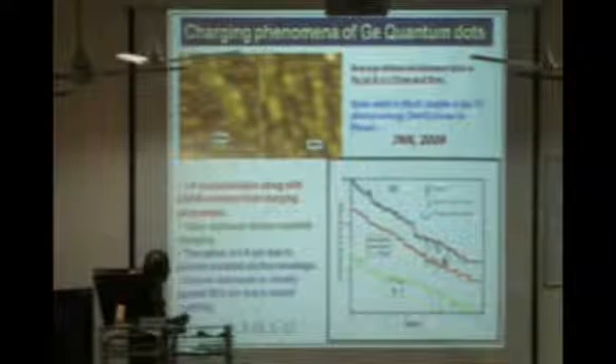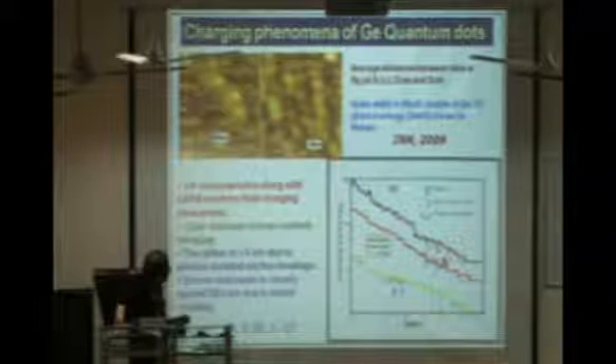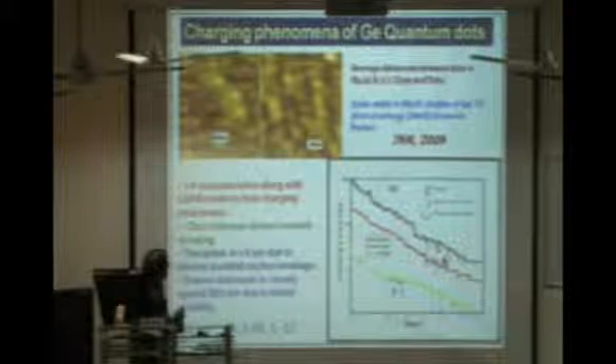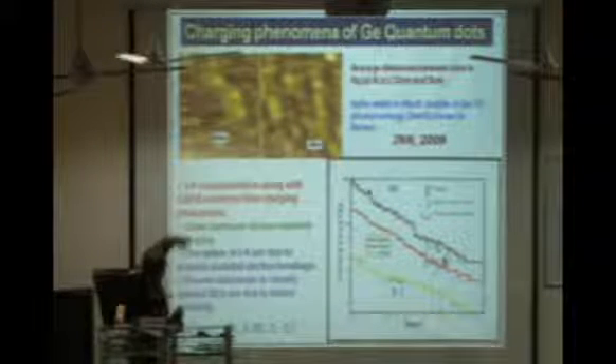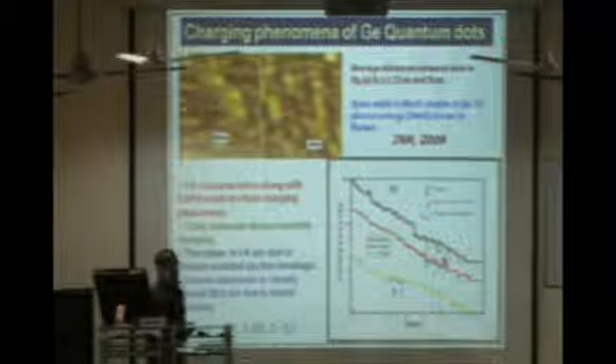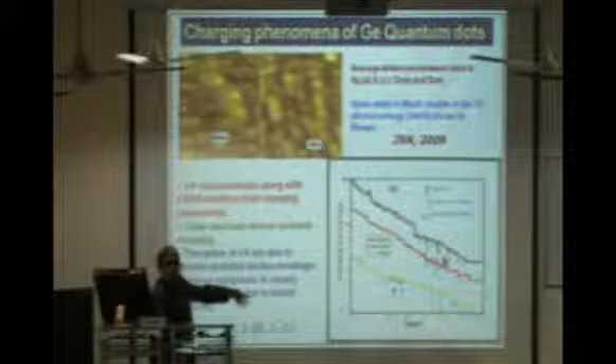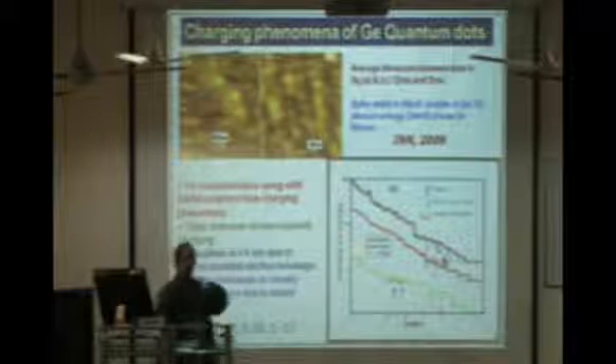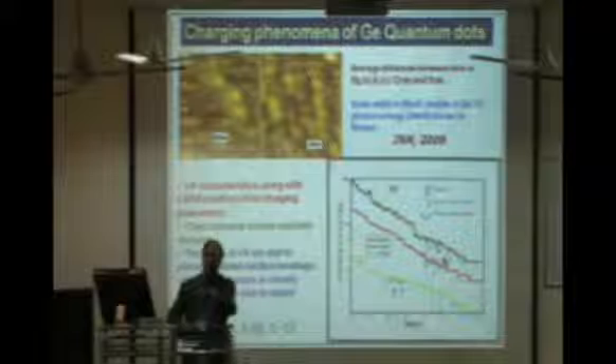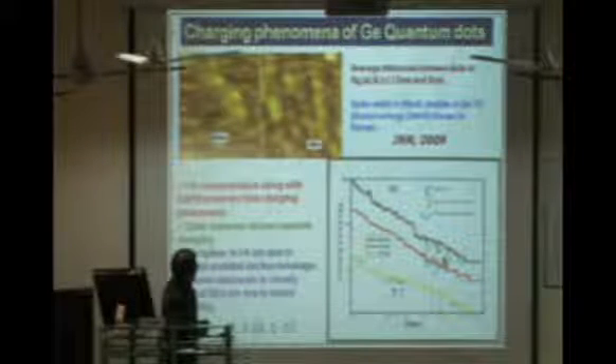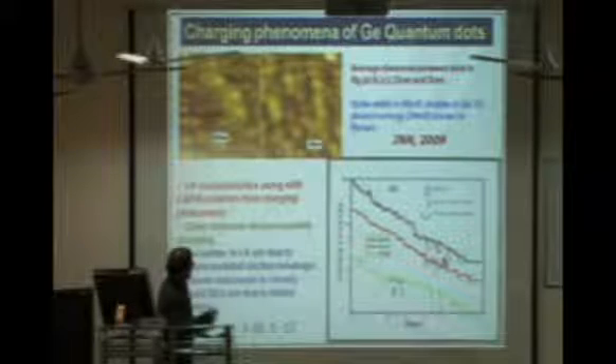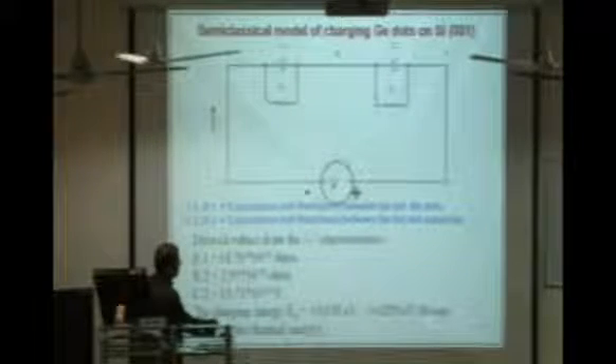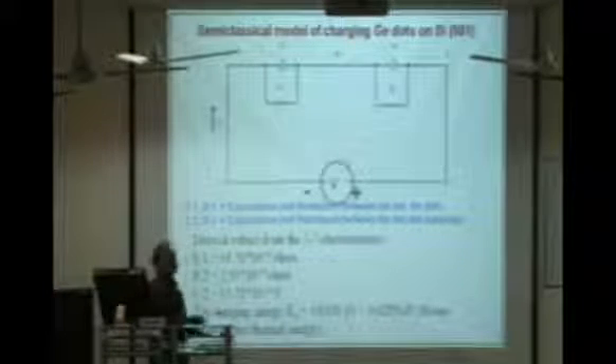In fact, as I was telling you, we also got some staircase characteristics when you took a conducting AFM tip on one of the single quantum dots. But as you see, there are a lot of noisy things also, because these were taken at room temperature. Normally people have demonstrated with STM that if you do low temperature STM experiments, you get very nice IV characteristics with a lot of staircase. But ours was mixed with a lot of other noise also. We have found this charging energy is about 0.053 electron volt, which is much more than the room temperature energy. That's why it could be achievable at room temperature. That depends on the size of these quantum dots.